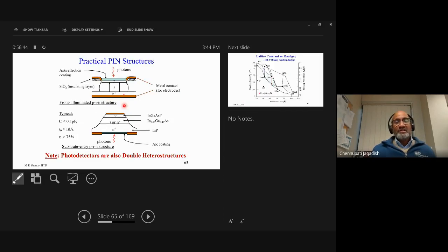So here is the actual structure, how it looks. Again, you grow the N-type layer, intrinsic layer, and P-type layer. You also put on some anti-reflection coating so that you can couple the light efficiently, and you have contacts to extract the carriers after shining light here. And here are some more details of indium phosphide and indium gallium arsenide based photodetectors, which are used for the 1.55 micron and 1.3 micron wavelength regions used for optical fiber communications. Again, double heterostructures and other things are also used here for a wide variety of purposes.